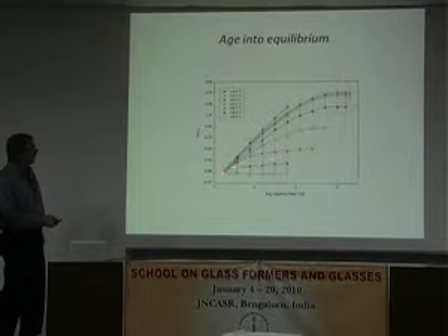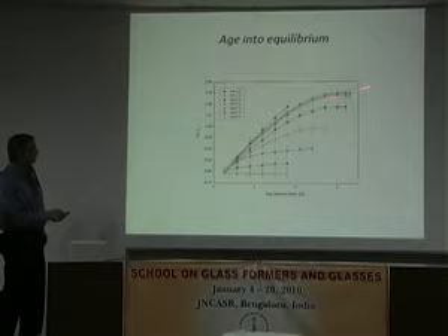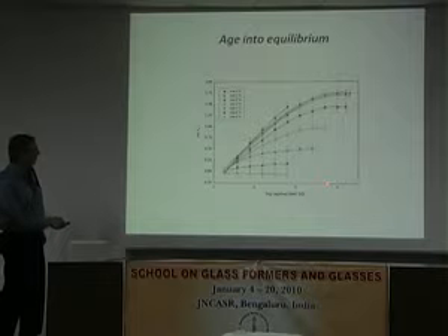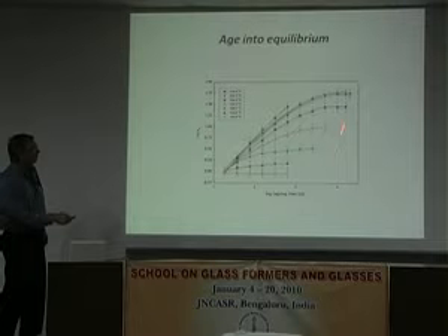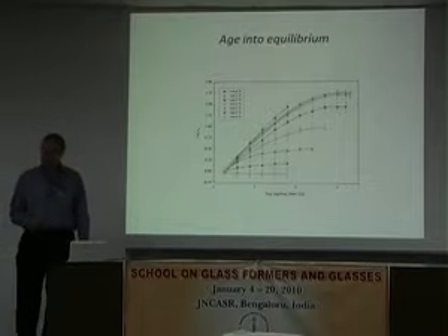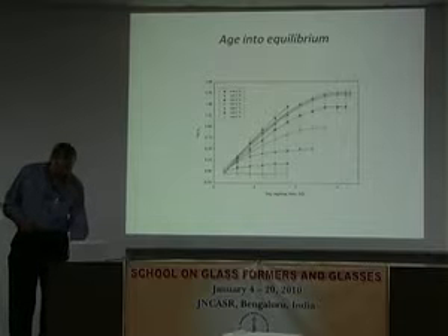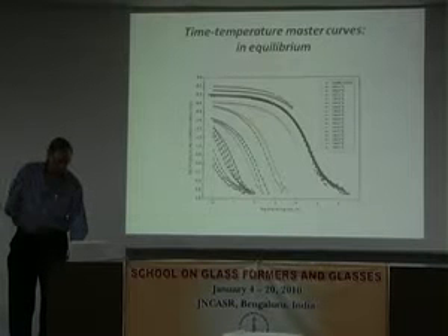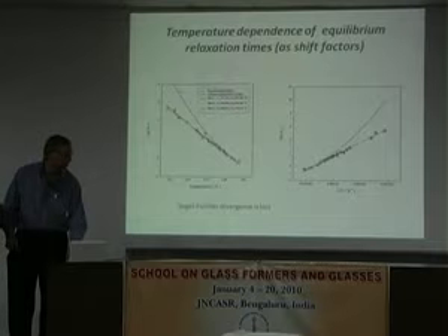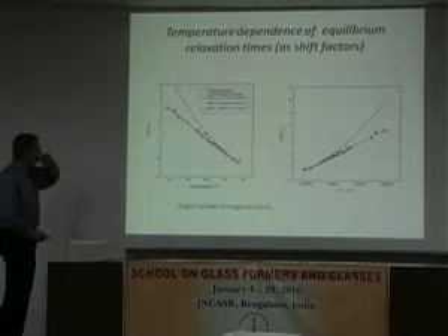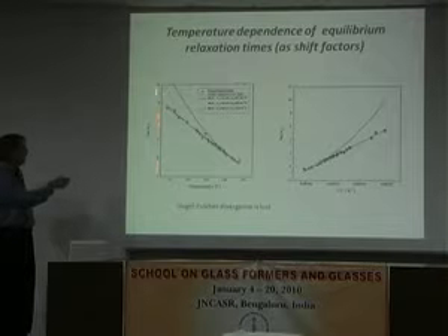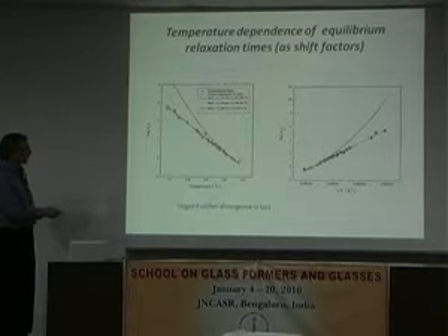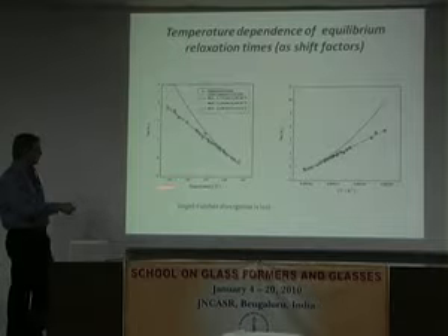And now we're going to watch what this response is as a function of temperature. They're in equilibrium. They're not changing. We want to know if, as we go down in temperature, whether or not this falls onto the WLF curve or Vogel-Fulcher curve or not. So this is just the time-temperature equilibrium master curves. And here's the behavior we see. Here's the log of that shift factor versus temperature. And this is how people in the polymer community do it, so we do it versus temperature.